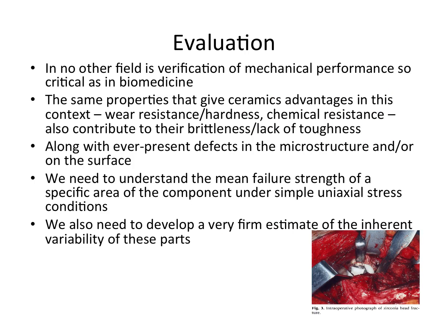And this can interface with things like grain boundaries. This is where grain boundaries can be a weak point because it can tear apart a grain boundary too, as well as a pore. So in this context, verification of mechanical performance is very critical here. The things that we like about ceramics: they're very wear resistant, they don't generate too much particulate when they're articulating against themselves. They're very hard, chemically resistant.